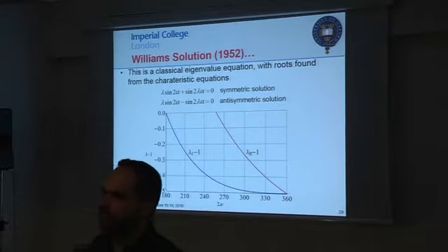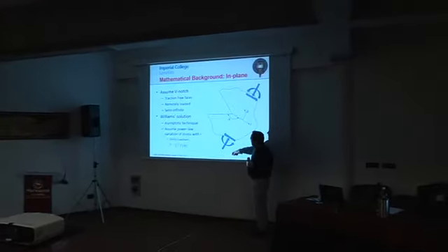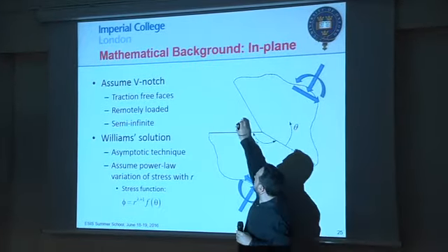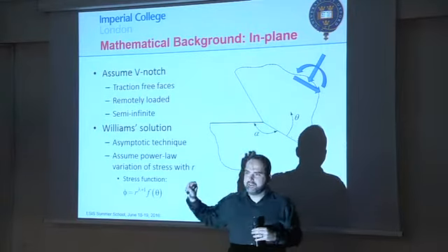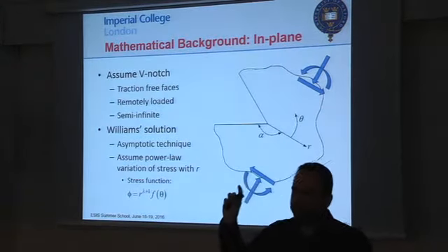Yes? So, if I understood well, there's a certain angle beyond which there's a sharp transition from a singularity to boundedness. So let's go back to the picture, because I think that's better. Set yourself to start from a crack, and let's make this angle very small. Starting from a crack, alpha is 180, 2 alpha is 360.